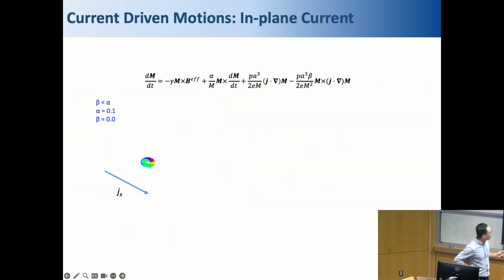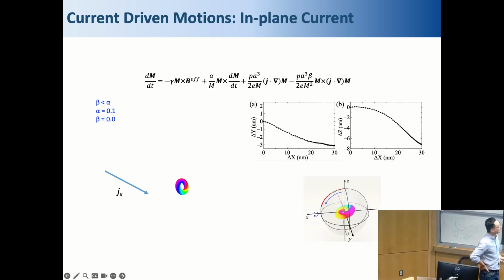So the last piece is the dynamics. The hopfion also has very interesting dynamics, and there are 3 dimensions, so the dynamics in 3 dimensions. We put a hopfion here, we apply a current, and we model this with the LLG equation, and we found this hopfion moves. But you see, this torus plane is rotating, and it also has some transverse velocity. So there is a hopfion Hall effect, and there's a hopfion rotation driven by this current. This is the case with beta smaller than alpha.